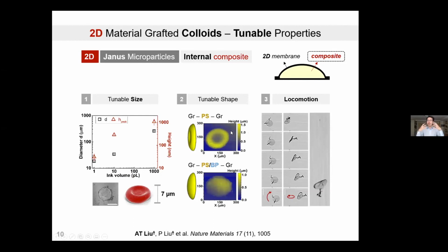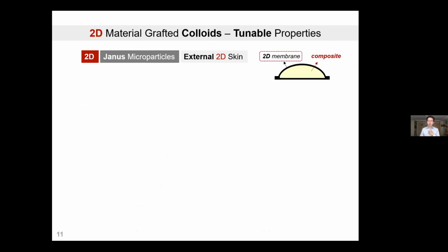By using nano magnetic particles inside the ink that we use to print, you can make the particles magnetic, and then you can control their locomotion using an external magnetic field. You can control their flipping, rotation, and translation. But I think the fun part here is that you can control whatever 2D material you use to make the top and the bottom of this dumpling that we're making.